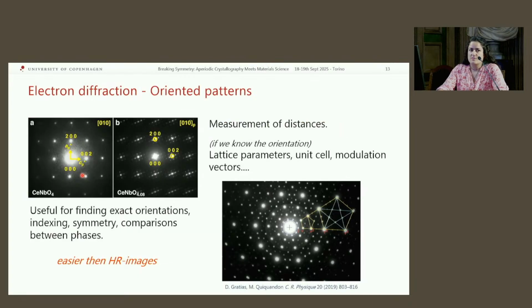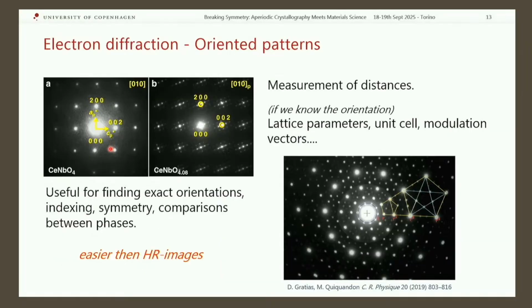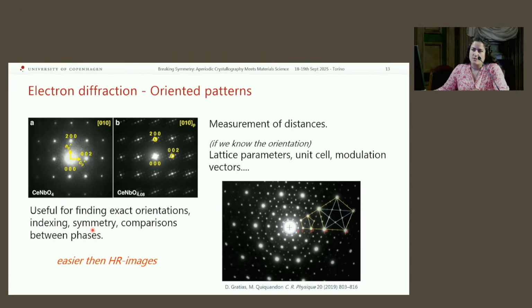We have seen some of these patterns before, so we can use them to, for example, compare phases. When they are similar, we can see these phases share the same basic lattice, but here we have many extra peaks. So this is a hint that it's some sort of modulated structure. And we can also measure the distances in the reciprocal space, and if we know the orientation of the sample, we can derive the unit cell parameters or any set of vectors that we need to describe our reciprocal lattice.